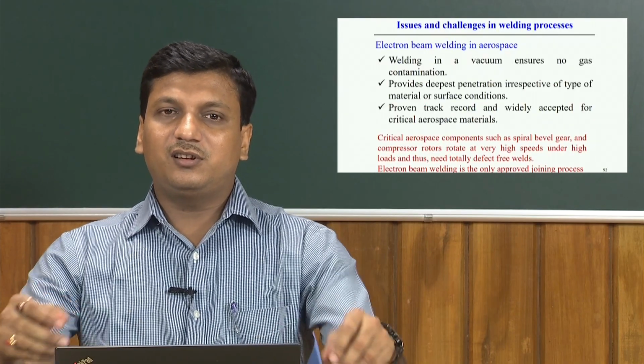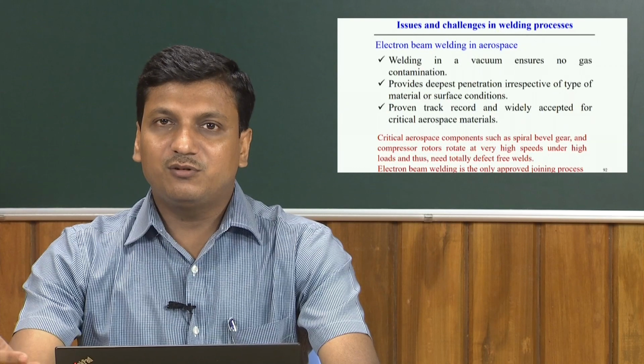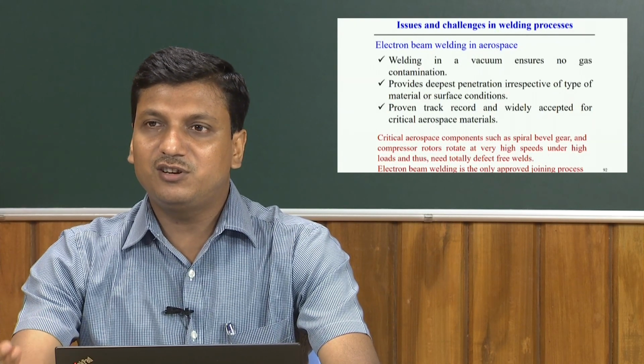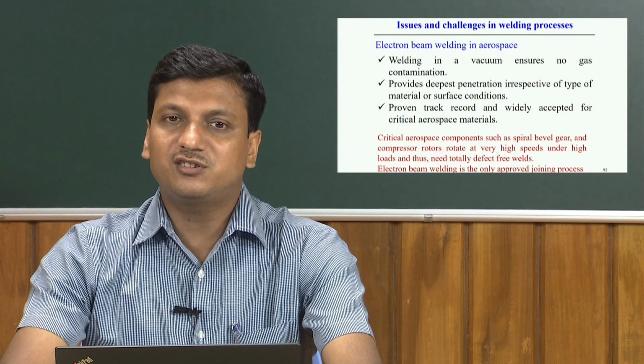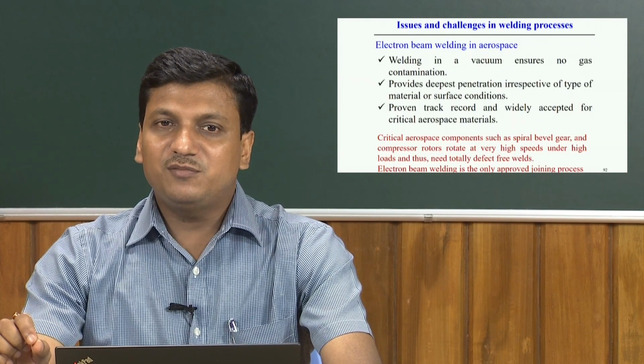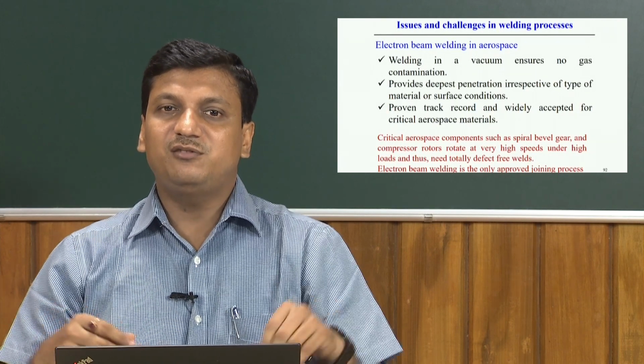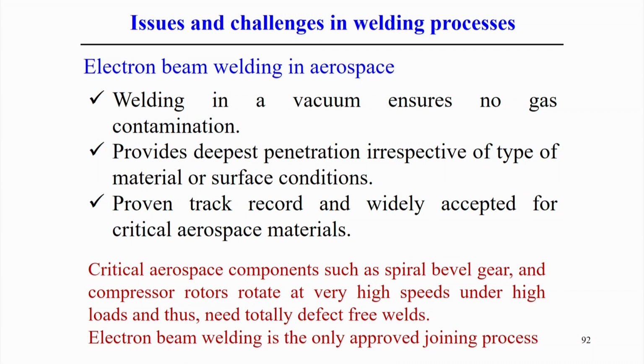And electron beam welding is another welding process, mostly used in the aerospace industry. Electron beam welding in aerospace is mainly performed in a vacuum, which ensures no gas contamination, and it provides very high depth of penetration irrespective of the type and surface condition of the material. It is a proven process and widely accepted for critical aerospace materials.